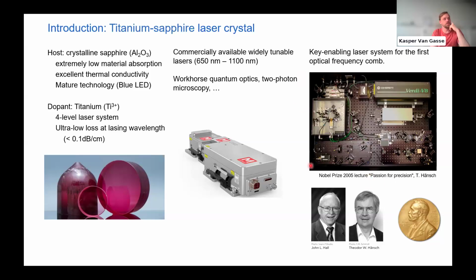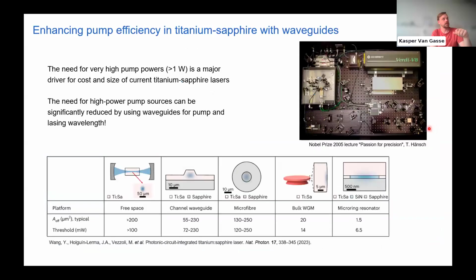And this is a picture of one of the first optical frequency combs. This is a titanium sapphire frequency comb. And actually, one of the challenges of working with titanium sapphire already becomes apparent from watching this picture, and that is namely that titanium sapphire lasers require an enormous amount of pump power. That has to do with the fact that the fluorescence lifetime of the upper lasing level is very short. But concretely, what does that mean? It means that you will need very big and expensive pump lasers.